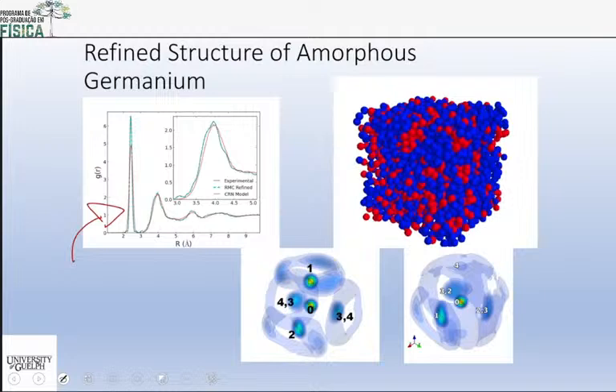And we said, hey, where are these atoms going to fall? Where are they going to go? And we got this picture on the top right here. What is that? Why do I have 2 colors? Because what we found was that this arrangement of atoms gave a perfect match to the experimental pair correlation function. And by doing a simple calculation, we found that the blue ones are atoms that had 4 neighbors, and the red ones were atoms that had 3 neighbors. And there were very, very few 5 neighbors or 2 neighbors. It was very amazing. Somehow, this model had come up with a solution that really just had 3 coordinated and 4 coordinated atoms. Or in this case, it was germanium.